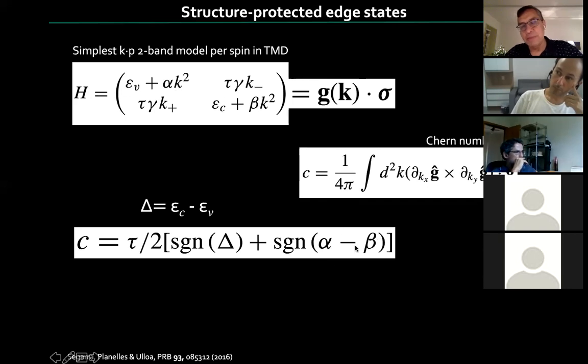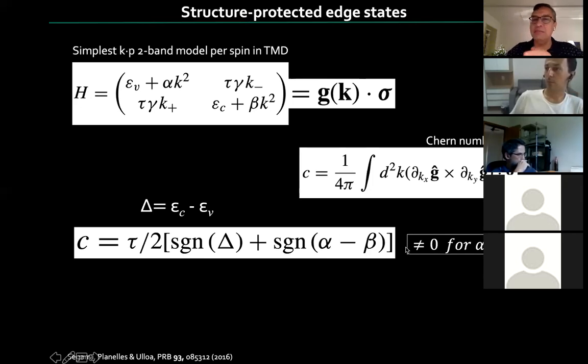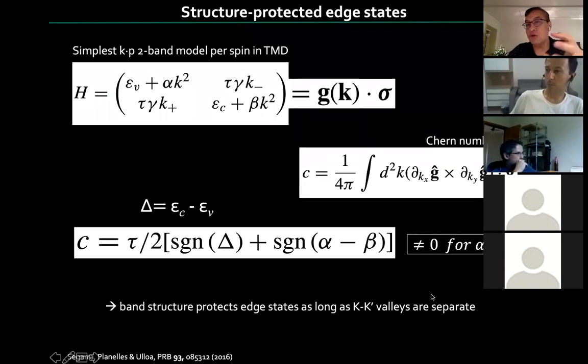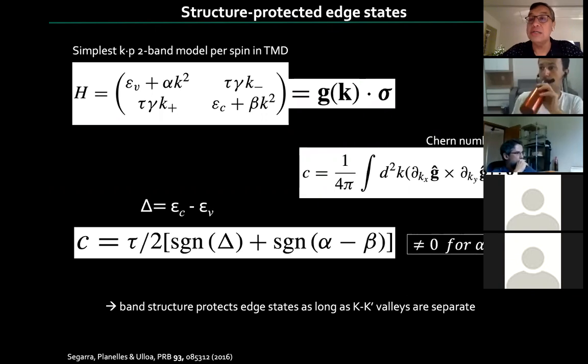And so the point is that depending on the values of these materials, you can in fact find that this Chern number per valley, for the Hamiltonian of one valley and one spin species, will be non-zero for alpha larger than beta. And so this tells you that for these conditions, the band structure itself protects these edge states,